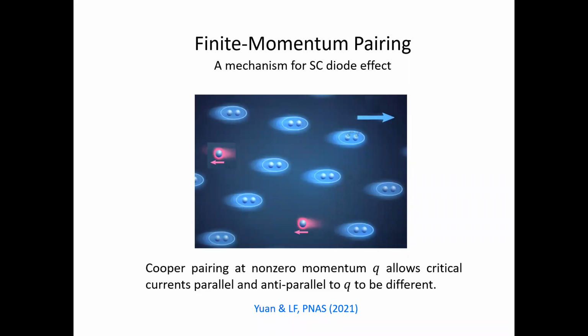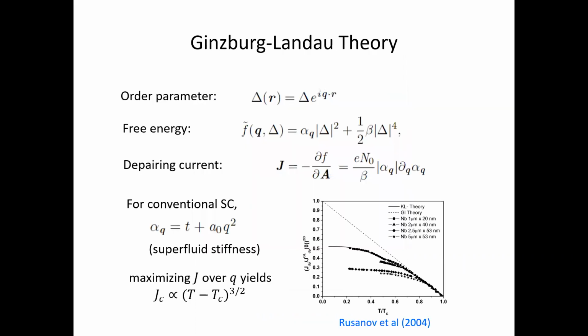However, we see that the presence of a finite Cooper pair momentum breaks the spatial inversion and time reversal symmetry. So this Cooper pair momentum basically plays a role similar to the electric field in the p-n junction. Okay, it sets a preferred direction. So in this case, based on symmetry, it should allow a critical current in the forward and the backward direction, parallel or anti-parallel to the momentum q. These two critical currents in general are now allowed to be different, and therefore this should allow a superconducting diode effect.